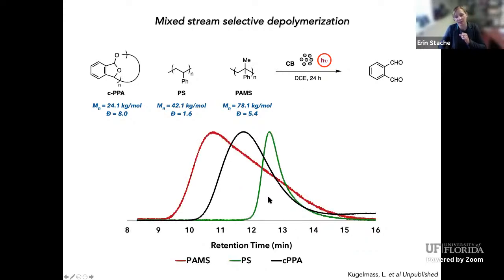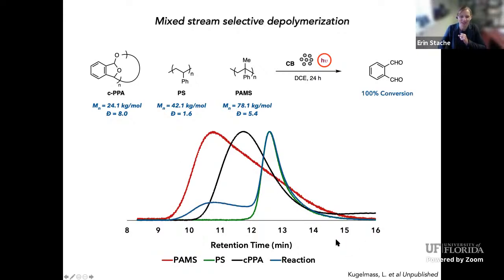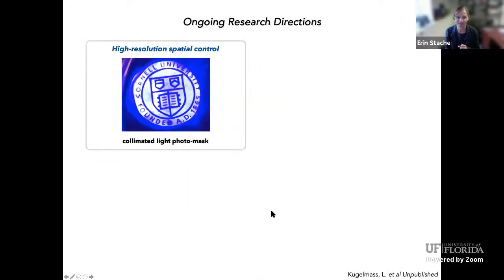This is the polystyrene. This is the poly(alpha-methylstyrene), a very broad sample. And then when we subject it to the reaction conditions in solution, we only see depolymerization of the cyclic aldehyde. You get 100% conversion to monomer, and you can see that the polystyrene and the alpha-methylstyrene are still intact, they have not been depolymerized, and we don't see any monomer in solution. And so now we're moving on to solid phase. Can we make films of these polymers, which of course, if they're not copolymers, are not going to phase mix? We're trying to develop ways to get these all into solid phase so we can test the depolymerization as a mixed stream.